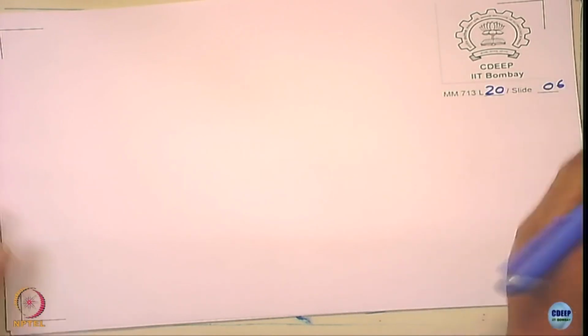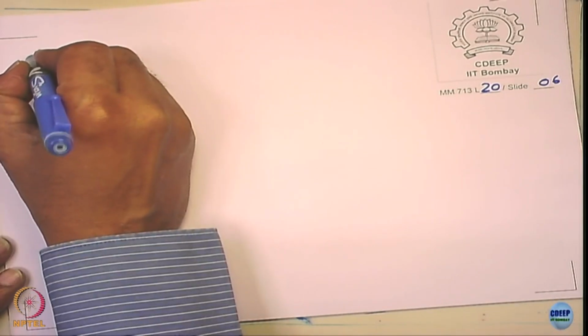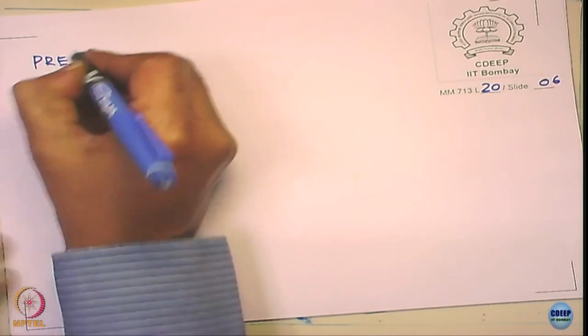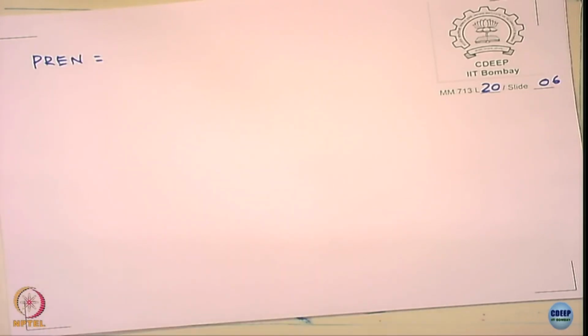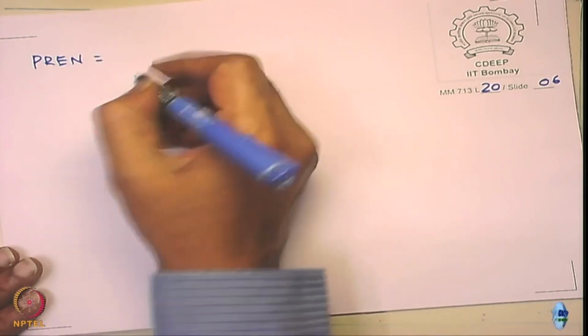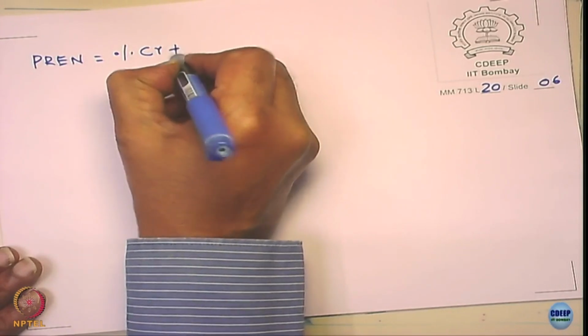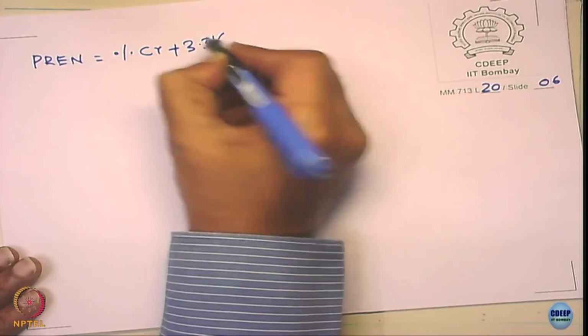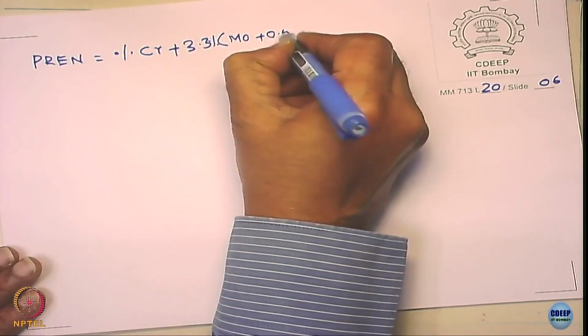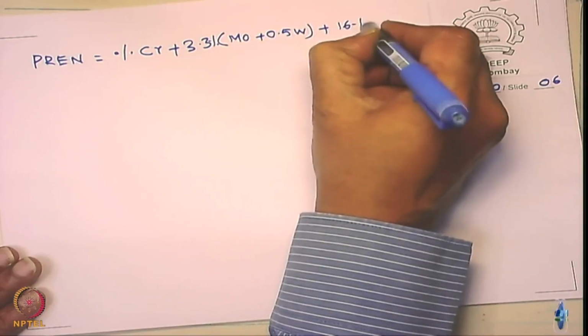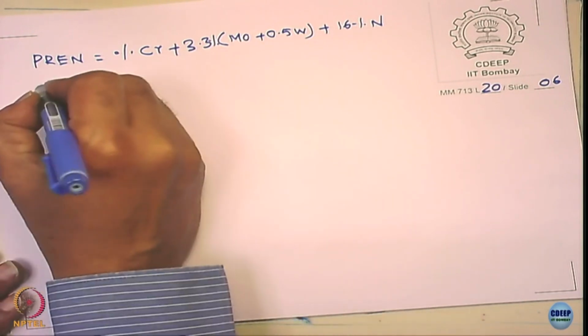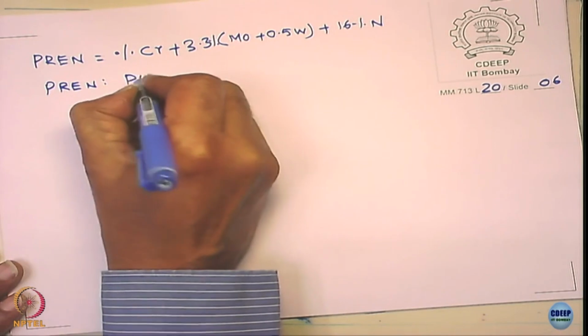Now if you look here, there is also an empirical equation to correlate alloy chemistry to pitting corrosion, that is using PREN. It is an index given as percentage of chromium plus 3.3 times the percentage of molybdenum, plus 0.5 of tungsten, plus 16 times the percentage of nitrogen. What is PREN? It is called the pitting resistance equivalent number.